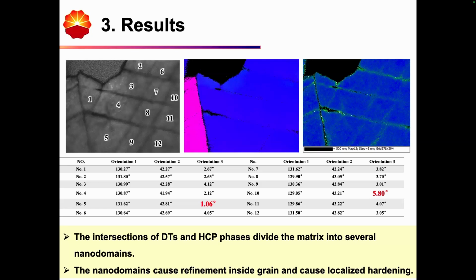Although it didn't show a very clear difference, within one grain it has been separated into a series of nanodomains, and the cooperative deformation of these nanodomains is slightly different. This kind of refinement inside one grain will also cause localized hardening, and this hardening will promote the propagation of the intergranular fractures.